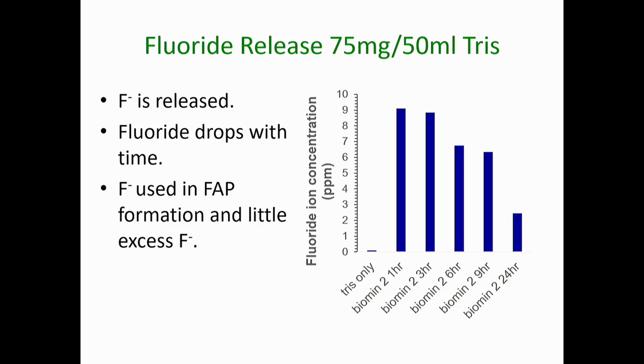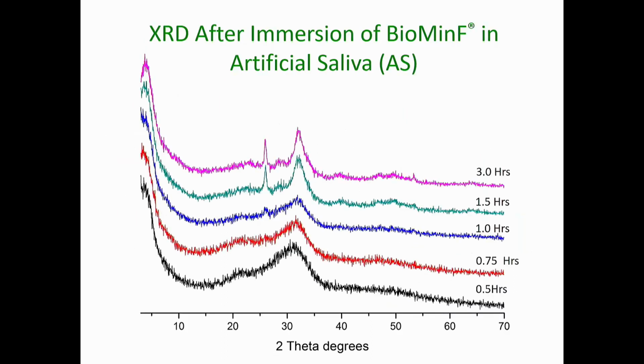Here we show the fluoride release for different time periods, and the fluoride drops with time. It's not flat top like my ideal schematic that we had before, and this is because quite a lot of the fluoride is used in fluorapatite formation. But you can see we still have 2 ppm of fluoride at 24 hours.